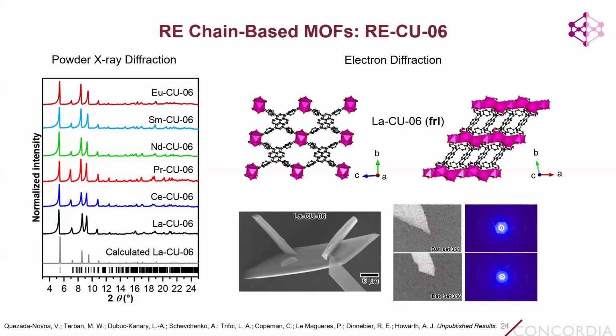So we were fortunate enough to be able to send one of these samples, the lanthanum CU-06 sample, to Rigaku, where Pierre collected some electron diffraction data for us. And he was able to solve the structure of this MOF, which is now shown here. And so pretty amazing that off of these really skinny plate-like crystals, we could get a full structure solution. This still kind of blows my mind, honestly, but I guess for people that are doing microED a lot, this is pretty normal now. But I think it's pretty amazing.